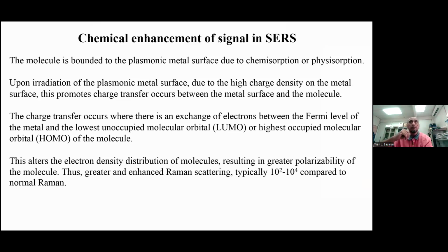Okay, so for example again, when you irradiate the laser onto the molecule, this will alter the electron density of the molecule. This will result in greater polarization, and that polarization will enhance the charge transfer from the metal to the molecule. Then you get an enhanced Raman scattering. That is basically around 10 power 2 to 10 power 4. So that is known as chemical enhancement.